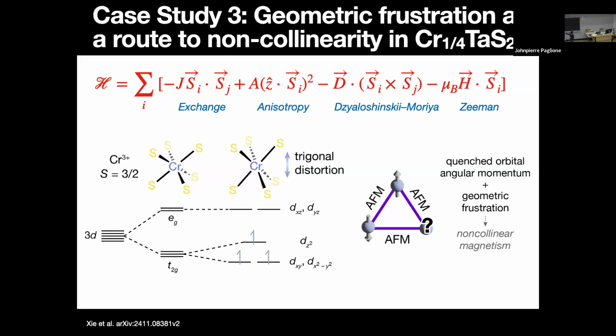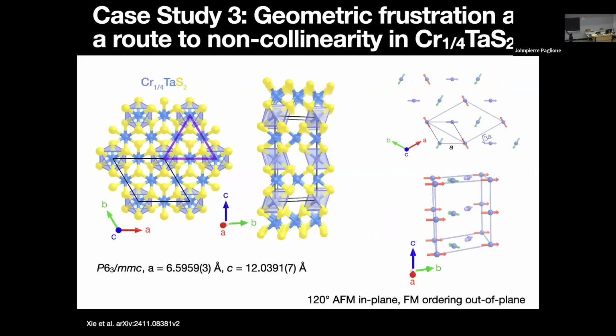And so instead, what this system does is that you have a canting of the spins, or a rotation of those spins in the plane, so that you form a 120-degree AFM in this material. And so this, I think, is the first in this family of materials to have a non-collinear ground state.